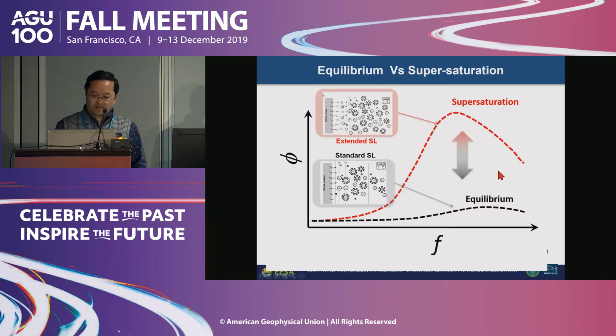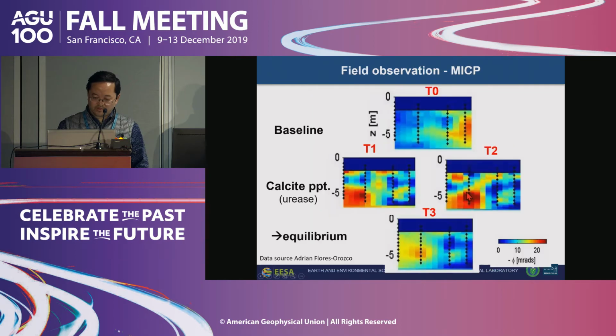So again, to summarize what we're observing in this cartoon, this shows the comparison between equilibrium and the supersaturation condition, where you have this shift of the stern layer structure going either from equilibrium to supersaturation or the other way around, which generates this behavior that is linked to the surface interfacial properties. And this actually is observed in the field.